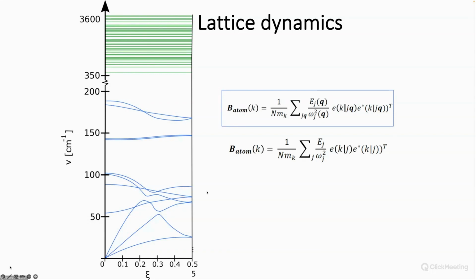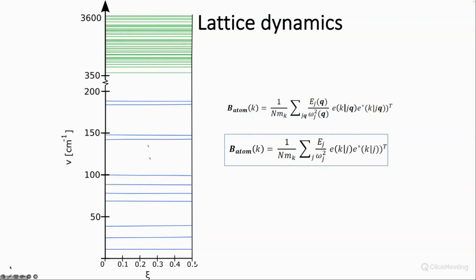So to make things a little easier for us, and in agreement with our elastic diffraction experiments, we basically treat each of these phonon modes and the frequency as a mean frequency for each mode. So we make things a bit less complicated and use the formula that we have down here, where we just sum over each mode one time, and we have the normal mode eigenvectors that describe the displacement of each atom in such a way that they do not depend on the wave vector, the wavelength of the phonon mode in the crystal.